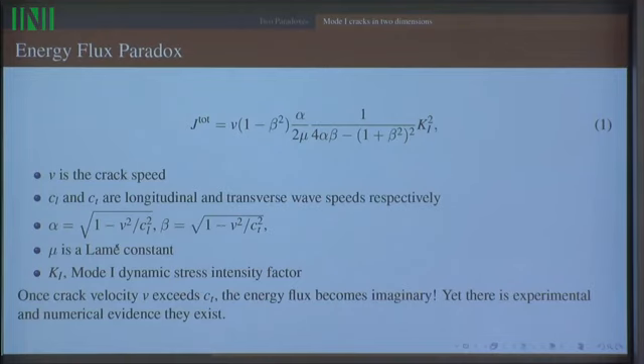Now, if you look at this expression, what you will see is that as soon as the crack speed passes the transverse or shear wave speed, the factor here becomes imaginary. And if that factor becomes imaginary, then energy flux becomes imaginary. And therefore, if you look, for example, in Freund's book on dynamic fracture, you will see the statement that cracks faster than the shear wave speed cannot exist. In fact, this expression goes negative at the Rayleigh wave speed. The denominator defines the speed at which waves will travel across a flat surface. So at that point, the energy flux would become negative, and that's been thought to be the upper limiting speed of a crack.